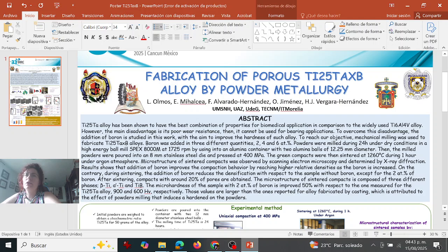The result shows that the addition of boron improves the compaction behavior by reaching higher relative densities as the quantity of boron is increased. On the contrary, during sintering, the addition of boron reduces the densification with respect to the sample without boron, of course, except for the 2 atomic percent of boron.